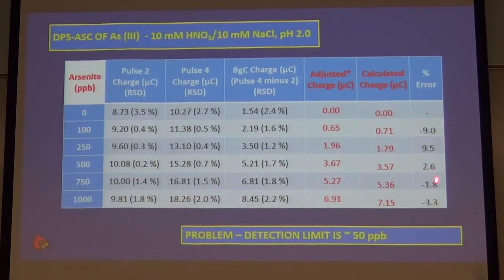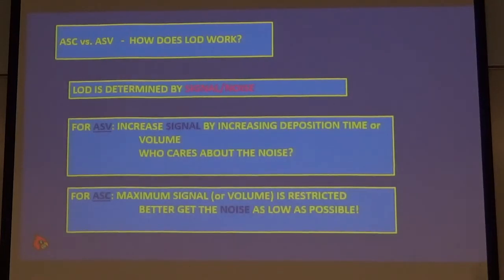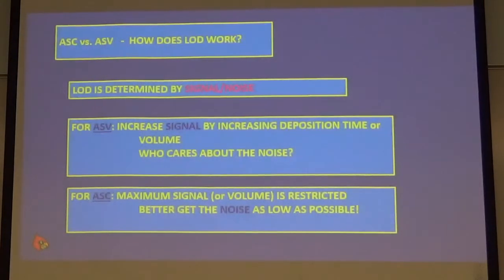Very reproducible. 10% is good for me. It's not good if I'm doing the experiment in the lab, but if it's out on the sidewalk somewhere, 10% is pretty darn good. But we were only down to about 100 ppb. We want to get down to 10 ppb for drinking water. With that system, we probably could have gone down to maybe 50 ppb, but we still want to go lower. Well, what's the problem there?